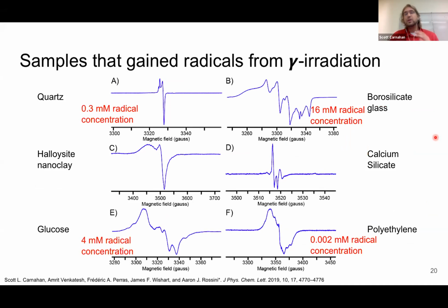We're able to get radicals in a bunch of other samples. I don't have time to talk about a ton of this now, but one that I'm going to talk about in a bit is borosilicate glass. The sample vials, we saw they changed color, but also in some other borosilicate glasses as well. We were able to get high radical concentrations in these, but DNP didn't work, we believe, because there's this high g anisotropy, as well as a fair amount of hyperfine coupling to boron-11.